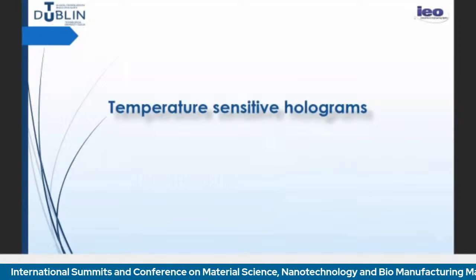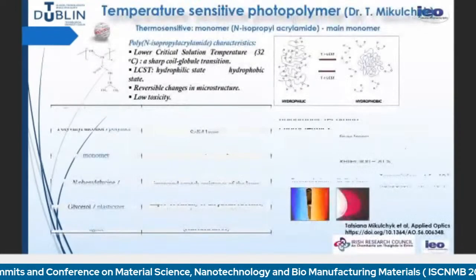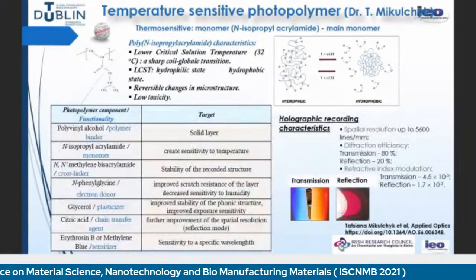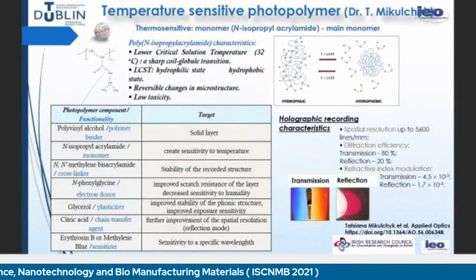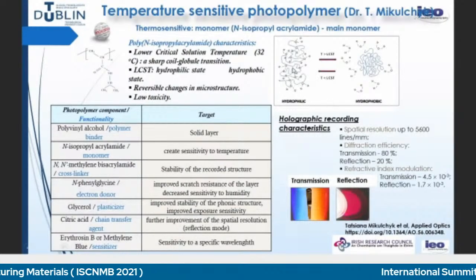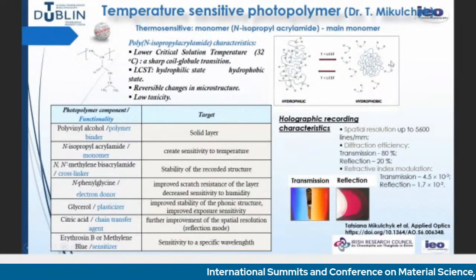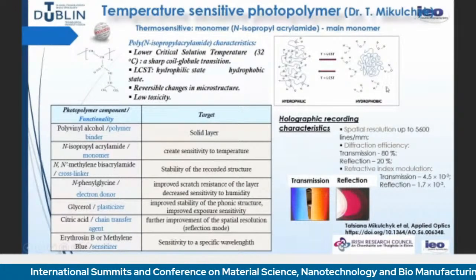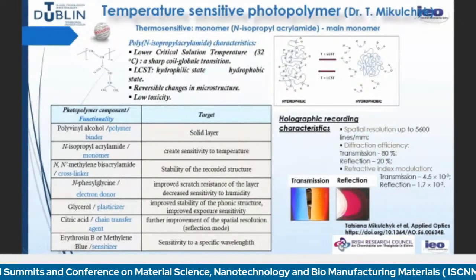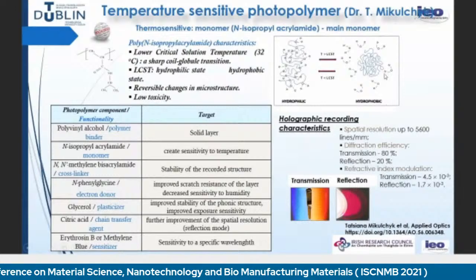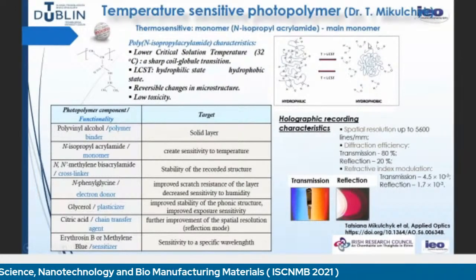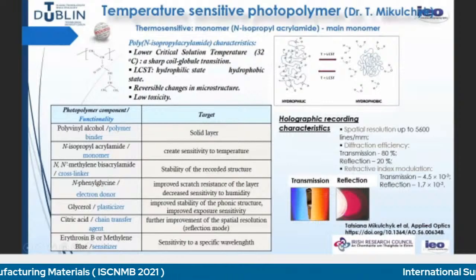So in terms of temperature-sensitive holograms, we use a very interesting material, which is polyNIPAM. This is a material with a lower critical solution temperature at around 32 degrees. And it switches from a hydrophilic to a hydrophobic state, where the water molecules are expelled from the polymer layer. And while most other materials experience thermal expansion, this material actually experiences thermal shrinkage when it goes above the critical solution temperature.